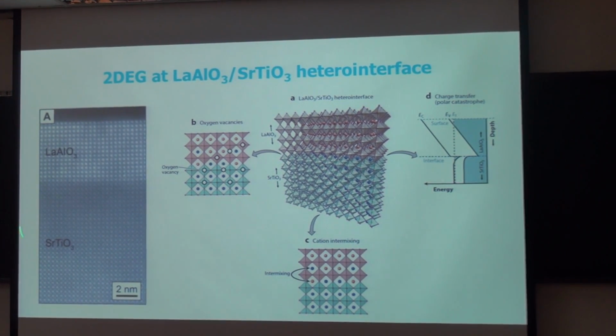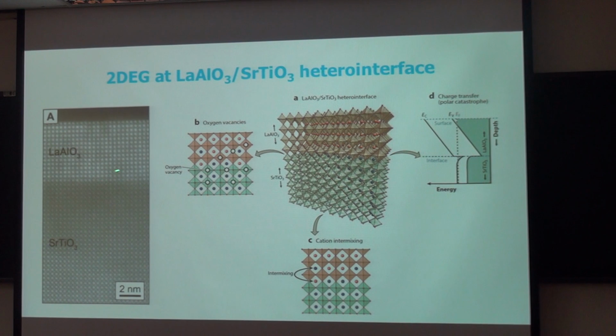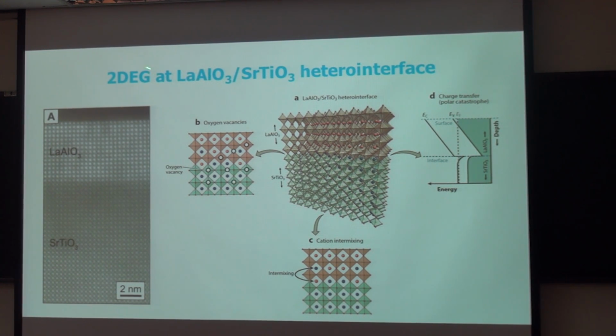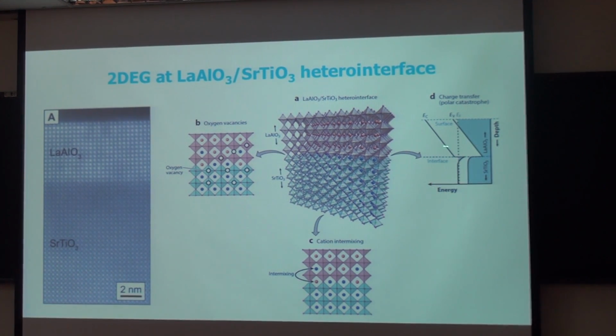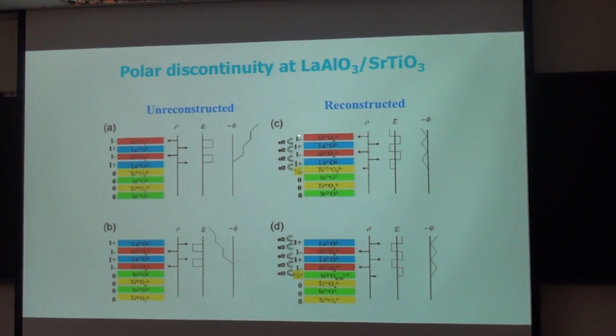Depending on the growth control situation, it is not strange to argue that the observed two-dimensional electron gas at the two-insulator interface has its origin in, for example, oxygen vacancy and cation intermixing. But the observation of critical thickness for the appearance of the two-dimensional electron gas has provided this picture that charge transfer by polar catastrophe plays a critical role.